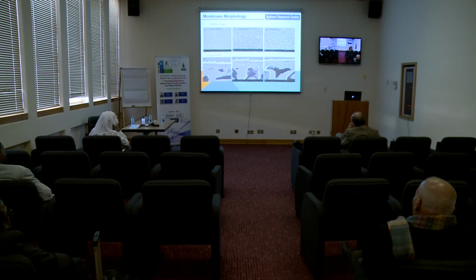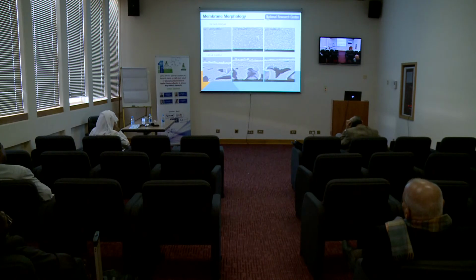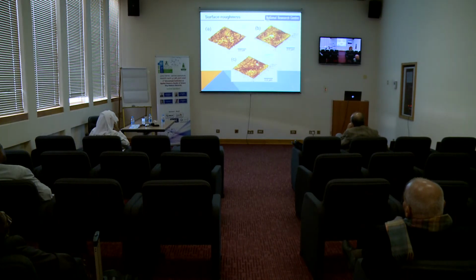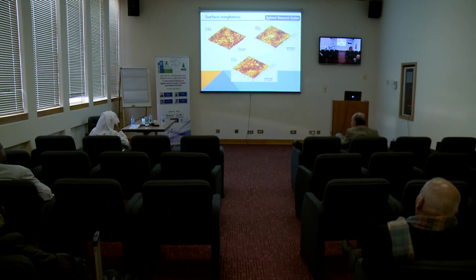The membrane morphology is, of course, very crucial for our separation work after this. So we have to look at the surface of the modified membranes. Here we have the surface images. We can differentiate between the ridge and valley layers, or shape, in the cross-sectional images, but the polyamidoamine 2 has a high and complete surface coverage with the new hyperbranched polymer. The surface roughness also confirms the last result, and we have more of the polyamidoamine on the RO membrane than on the RO membranes modified with the polyamidoamine solution in methanol.